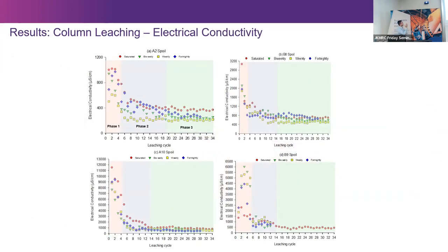So four different spoils, A2, B8, A10, and B9. What we found is the electrical conductivity release pattern in all four spoils was similar: we saw phase one release, phase two, and phase three. Phase one was the release pattern wherein you have release of the soluble salts that are already sitting on the rock surfaces, also known as first flush. And then you have this steady decline as phase two, and then quasi-steady conditions developed within phase three. So what we've done is calculate the decay values at each stage throughout the leaching process, and we know how salts would decay at what phases. I'll talk about that in my later slides, but that was an important understanding of how the salts would leach out.